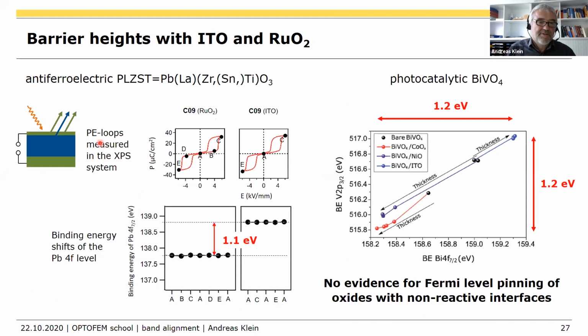Here are some other examples. This is antiferroelectric lanthanum doped lead zirconate stannate titanate. We did something where we can take our material, we make a very thin electrode on top. That means we can measure the PE loop in the XPS system. So this is our antiferroelectric PE loop. And then we can stop the loop at a certain position and do an XPS measurement and determine our Schottky barrier height. And again, you see this is with ruthenium oxide and ITO electrodes. It's again 1.1 eV difference.